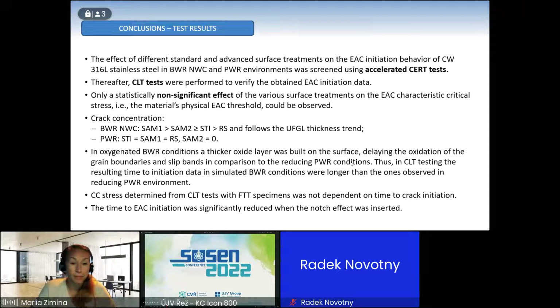In oxygenated BWR condition, a thicker oxide layer was built on the surface, and it delays the oxidation of the grain boundaries and slip bands when compared to the reducing PWR conditions. That is why probably the constant load testing resulting time to initiation data in simulated BWR conditions were longer than the ones observed in the reducing PWR environments. Critical stress determined from constant load testing with tapered specimens was not dependent on time to crack initiation, and the time to crack initiation was significantly reduced when the notch effect was inserted.